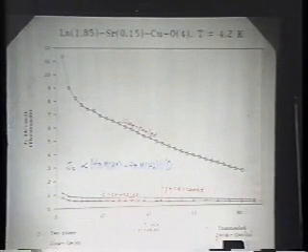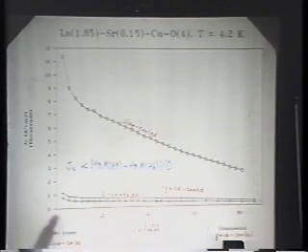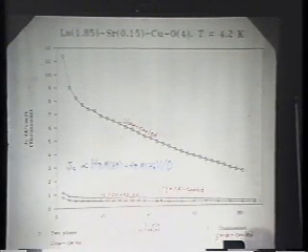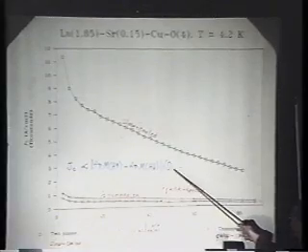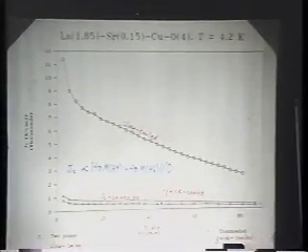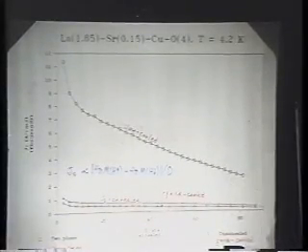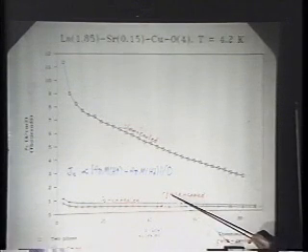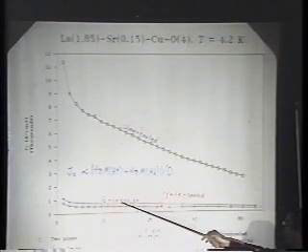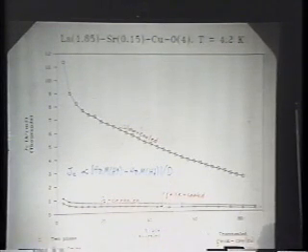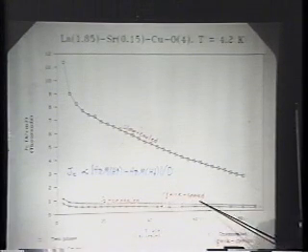These effects can also be correlated with the observed critical current densities. We measured these critical current densities in a manner described earlier by Doug Fenimore, by measuring the hysteresis in the magnetization, and for that you also need a characteristic dimension of the sample. But what's interesting here, and perhaps very relevant, is the fact that both the quick-cooled sample, which is single phase but very defective, and the O2 annealed samples, which are single phase with no defects other than the grain boundaries, those critical current densities are very low.